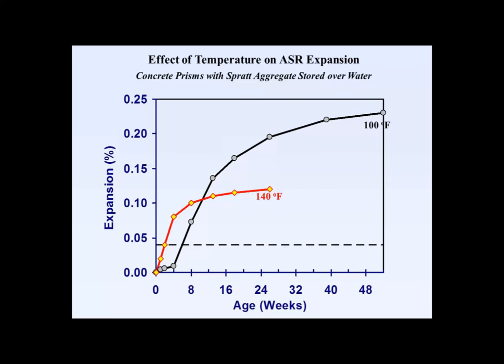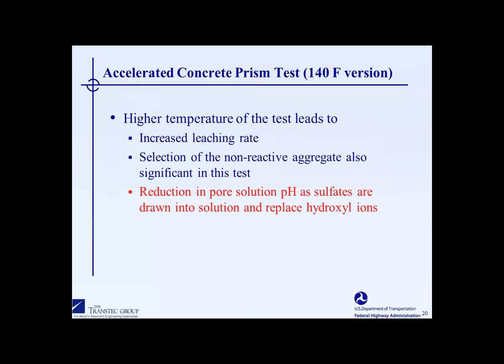But what ends up happening when you run this test at higher temperatures is shown here in the next slide. First of all, we've done testing within our groups to show that we in fact get more leaching at higher temperatures. So that's magnifying an issue that I already discussed. Also, when evaluating a coarse aggregate and using a non-reactive fine aggregate, like we routinely do for the concrete prism test, we've noticed that non-reactive sand plays a very, very large role. I don't really have time to discuss it much today, but there have been a few publications in literature that speak more to this issue.